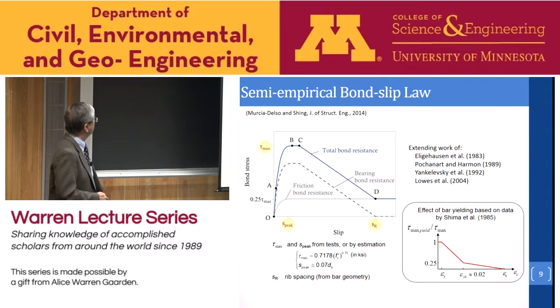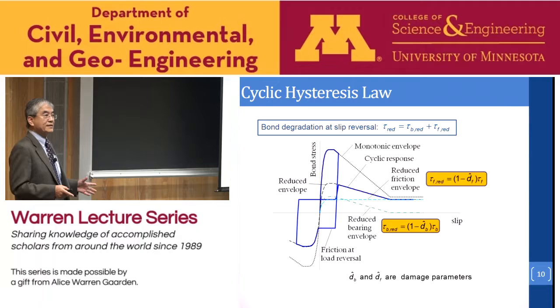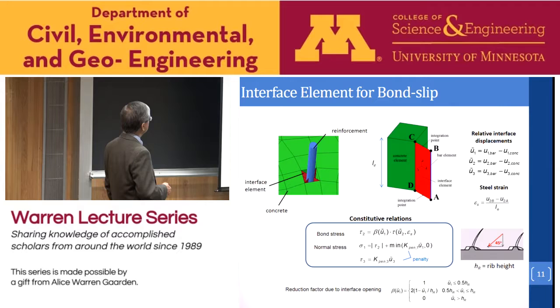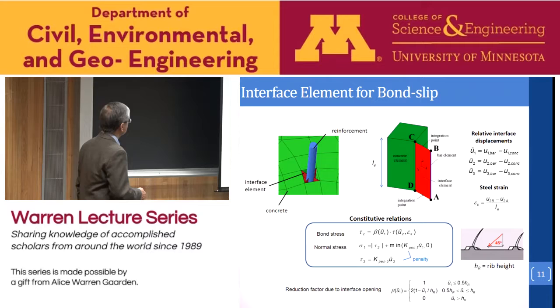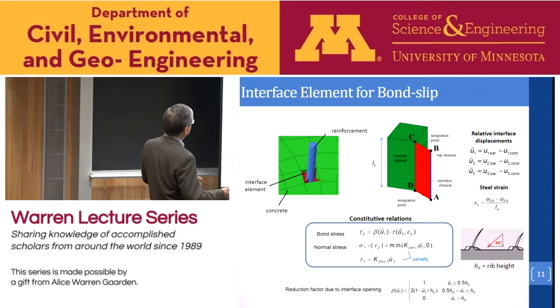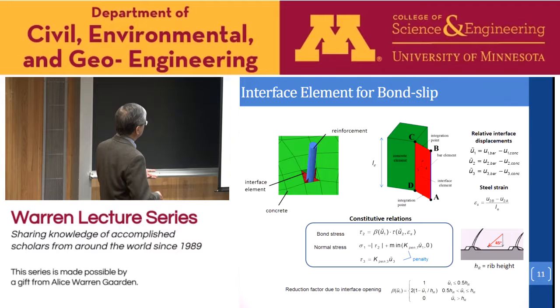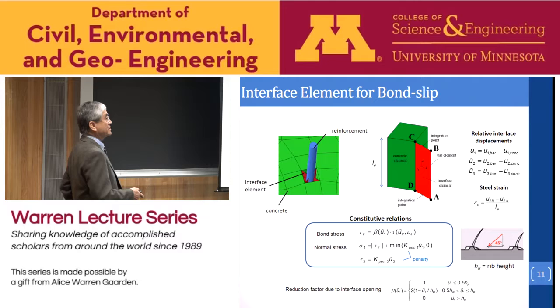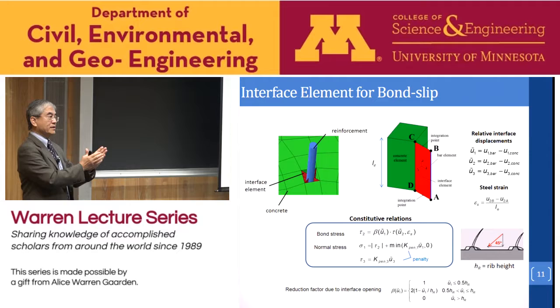Okay? So we implement this model as a zero thickness bond slip law in the Abaqus program. So this just shows the interface. Actually, it's a zero thickness interface. Okay? So in this model, the bond stress is equal to the product of these two. This is the relation between the slip and the stress, and also the influence of the steel. And the other parameters, the beta parameters, account for the opening, the gap, separation between the concrete and the bar, as the bar slips because of the wedging action of the bar ribs.